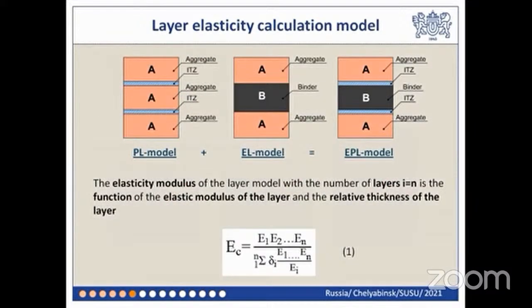On the basis of composite deformability specifics, layer deformation models of different structure types are suggested. The matrix layers, depending on composite type, can be the ITZ only with mostly plastic properties, type PL, the binder only with mostly elastic properties, type EL, or the binder and ITZ with viscoelastic properties, type EPL.